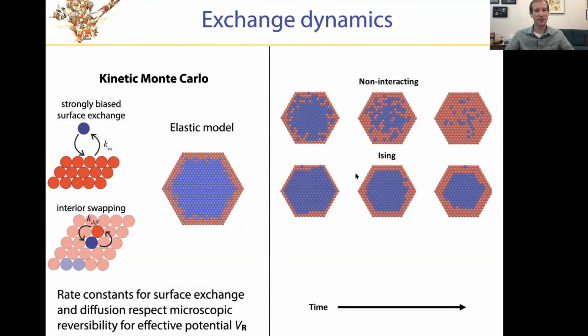these exotic modulated order phases rearing their head. Even though these aren't stable at equilibrium, they play a large role in the dynamics of exchange. You can see that exchange here is much more facile, even though there is a front proceeding through this. This effective encouragement of mixing on microscopic scales that comes from those elastic interactions actually really promotes the advancement of that front to proceed much more rapidly than I would expect if I only had these local chemical preferences.